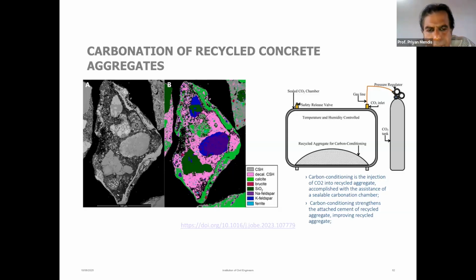So we are passing carbon dioxide through it, and that carbon dioxide will convert the layer around the aggregates to a very stiff calcium carbonate. So the captured carbon dioxide from the cement production process can be used to improve the recycled concrete aggregates. Our initial trials show that we can increase that percentage to almost 100% recycled concrete aggregates if you have carbonation. So that's another area where we can really see things happening in the world in the next few years.